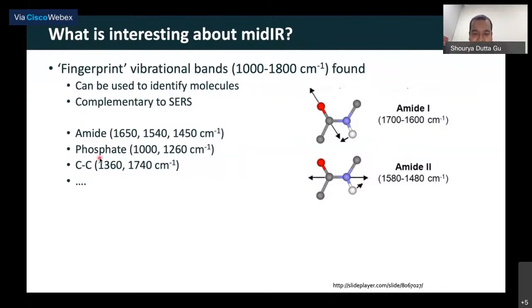Since they are fingerprint bands, by looking at where these bands occur, you can say what these molecules are. If I give you two examples, look at the amide bond, CONH2. This has multiple vibrational features. The amide 1 occurs typically around 1650, and the amide 2 occurs around 1540. If these peaks are present, you can say you have a molecule which has amide bonds. Similarly, you can look at the phosphate bond, the carbon-carbon bond, or the bonds corresponding to OH and so on. However, if you have done FTIR or looked at the FTIR setup and the sample preparation, you know that you need a very thick sample or a high concentration sample.